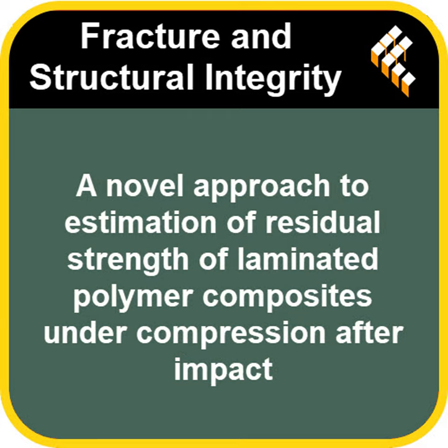And these diagrams very clearly revealed three distinct characteristic stages. First, there's stage one, insensitivity to impact. Up to a certain point, around 15 to 20 joules of impact energy in their tests, the impact had surprisingly little effect on the material's remaining strength. In fact, for many of the 090 specimens hit with just 10 joules, when they compressed them afterwards, the failure actually happened outside the small damaged zone. The damaged bit was still strong enough. This confirms there's a crucial lower threshold, meaning minor bumps aren't necessarily a structural death sentence.